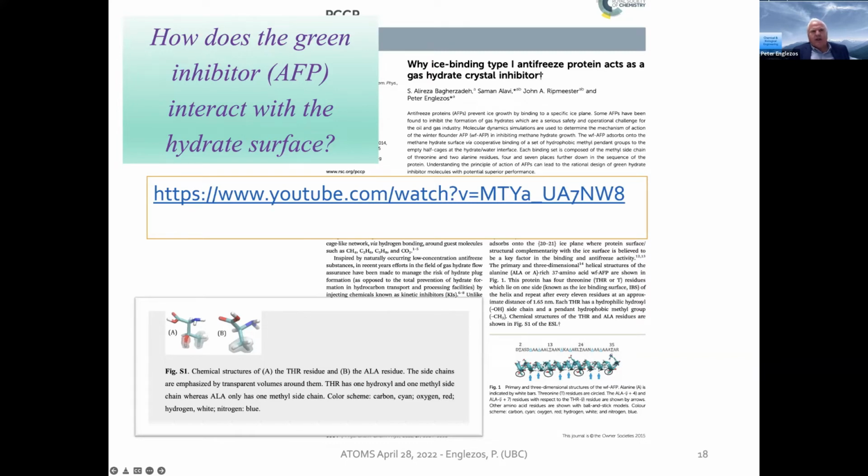It was thought that the inhibition of ice was due to hydrogen bonding because of this OH. But it was actually shown, by mutating the protein and creating one without OH, that hydrogen bonding plays really a minor role, and it is an adsorption between the ice binding surface of the protein and the ice itself, not hydrogen bonding, just an adsorption interaction.